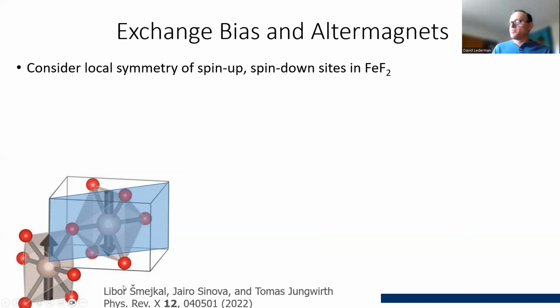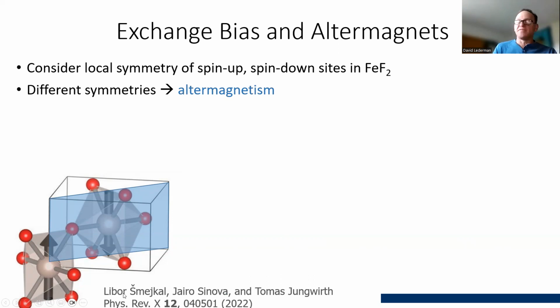And the point by Jairo Sinova and others who have been working on this, and Thomas Jungwirth, is that they make very interesting predictions about, for example, an antiferromagnet that's conducting: it would have very interesting transport properties. In fact, you could get a spin polarized current in an antiferromagnet, even though the antiferromagnet does not have a net magnetization.